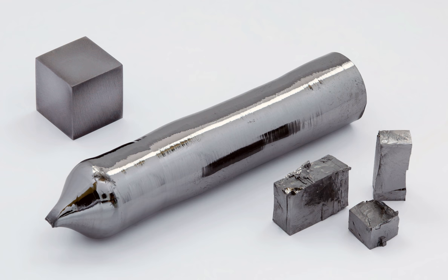Tantalum receives far less attention in the environmental field than it does in other geosciences. Upper crust concentrations (UCC) and the Nb:Ta ratio in the upper crust and in minerals are available because these measurements are useful as a geochemical tool. The latest values for UCC and the Nb:Ta ratio in the upper crust stand at 0.92 ppm and 12.7 respectively. Little data is available on tantalum concentrations in the different environmental compartments, especially in natural waters where reliable estimates of dissolved tantalum concentrations in seawater and freshwaters have not even been produced.